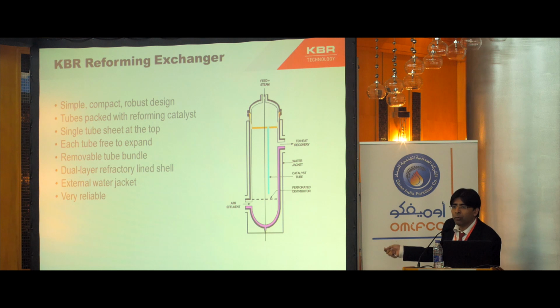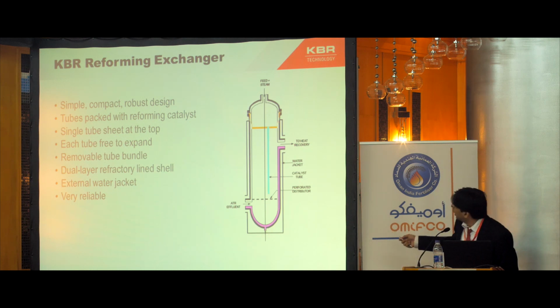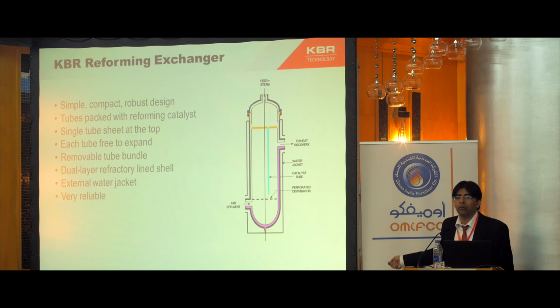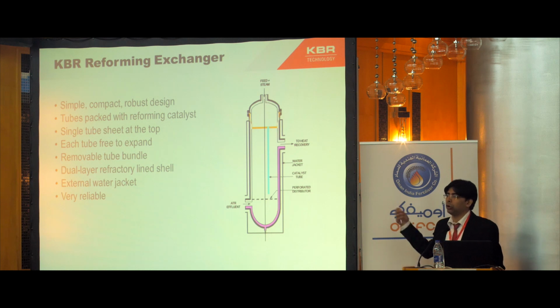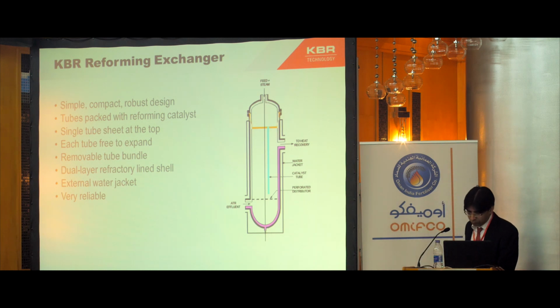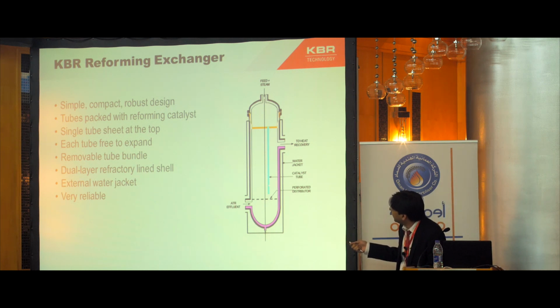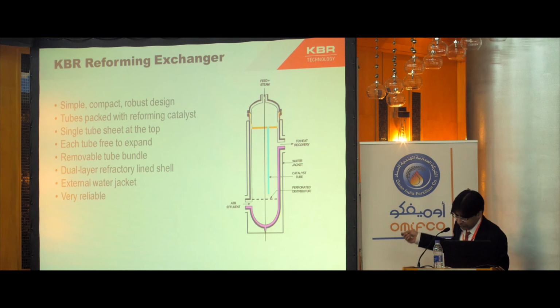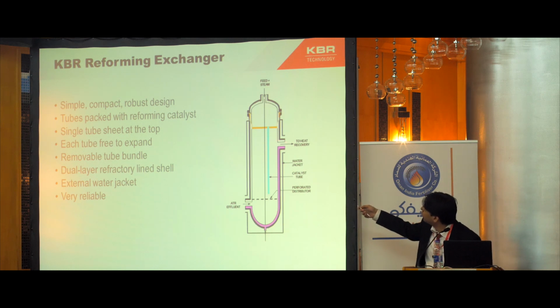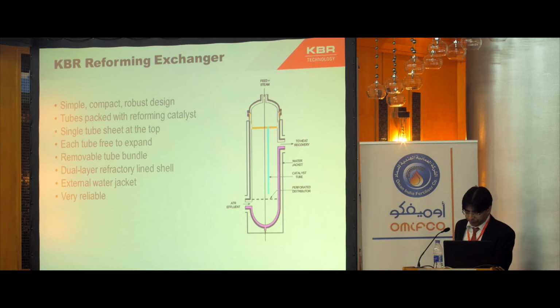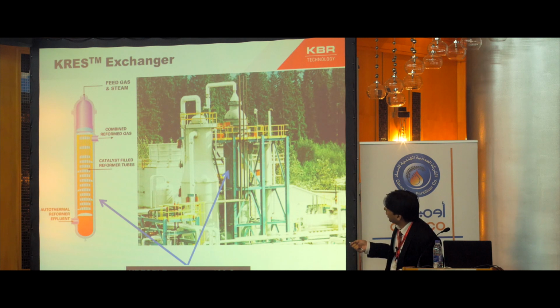This bundle is completely removable, just like a waste heat boiler. The tube sheet is located at the cold end of the heat exchanger. The shell is also protected by water jacket along with dual layer refractory, which is also very similar to waste heat boiler design. The catalyst is contained inside the tubes, simple, without the use of shell tubes. So it's very reliable and high performance. High maintainability is also kept by having this bundle removable easily. This is 100C, basically we call it 100C in our nomenclature. This is the KRES which was installed in one of the sites in USA.